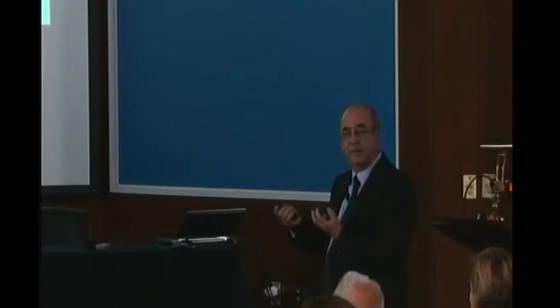So then the last part is the volume change. As I told you in the beginning, we wanted to use these materials in order to use the volume change. So the idea is the following. If you look at the structure of your system, when you go from the low spin to the high spin form, you have a change of the volume by 13%. This is just classical structural analysis by X-ray diffraction.